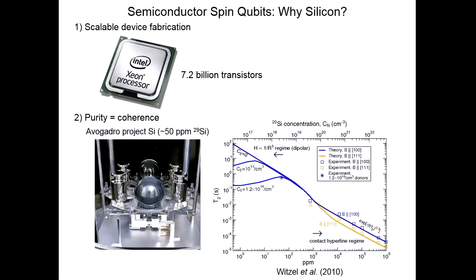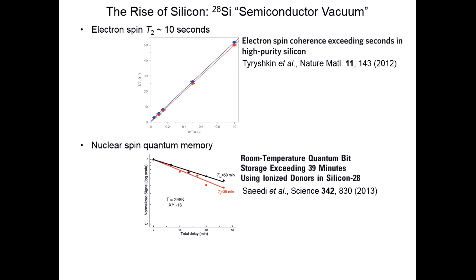But as you increase the isotopic purity and get rid of more of the unwanted, bad actor silicon-29, the coherence time, in theory, will just grow and grow, and you're expected to see T2 coherence times on the order of seconds. So, fortunately, there's a project in the EU to make a kilogram standard out of silicon, to make this bowling ball. And little offcuts of this ball from what's called the Avogadro project ended up in John's lab and Steve Lyon's lab and Mike Thewalt's lab, other labs throughout the world. And some scientists did measurements on those. And the neat thing is that if you really measure T2, this is real theory and it works. You can have coherence times in isotopically enriched silicon that approach second-long time scales.